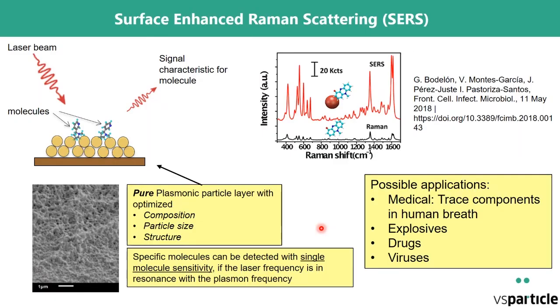Surface enhanced Raman scattering is a very, very strong method to make sensors, especially for organic molecules, and detect even single molecules if it's done in the correct way. Important for this technology is that we have plasmonic particles, and they have to have the right composition, the right size, and the right structure. Of course, we can do this by using spark ablation together with printing. What happens then is that a laser beam comes into resonance with the plasmon frequency, and if there are molecules at the surface, then exactly where these molecules are at the surface of the particles, the electric field of the radiation is amplified by a very, very high factor.